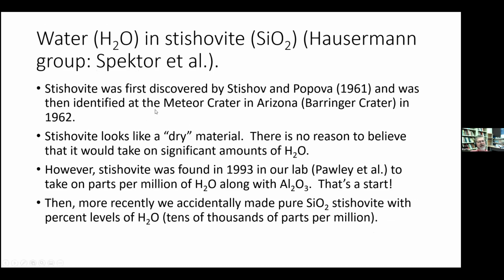Okay, another discovery we had at ASU, accidental discovery, I would say, because we were trying to grow zeolites at high pressure. Ulrich Hausermann is a chemist, a solid state chemist, or he's an inorganic chemist who's got really good instincts for projects, but was trying to grow some kind of porous materials at 9 GPa. But even at low temperature, like 400 degrees, 300 degrees, we were getting stishovite, which you could never get without water. Stishovite, you need at least 800 to 1,000 degrees to make stishovite from coesite or quartz or SiO2 glass. We were very surprised to find stishovite at such a low temperature, but then even more surprising, the peaks were shifted a lot. And it just was, especially the peaks involving the A-axis.